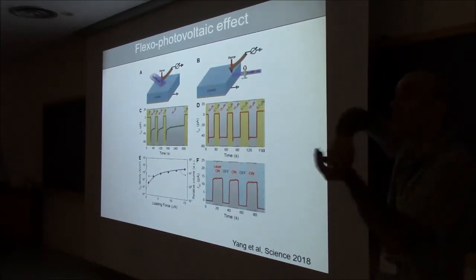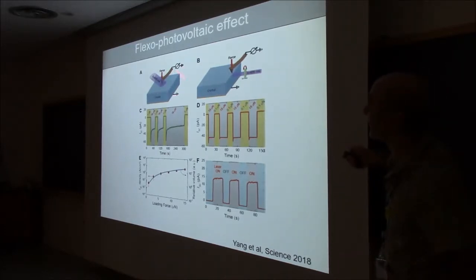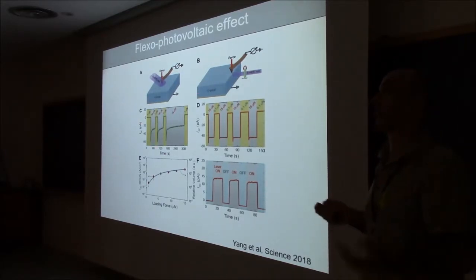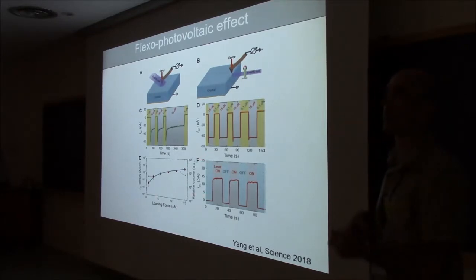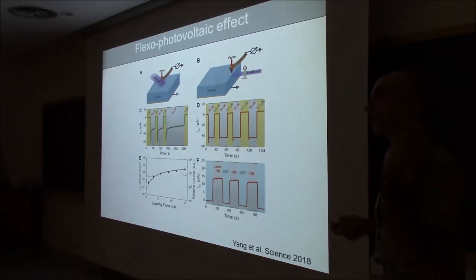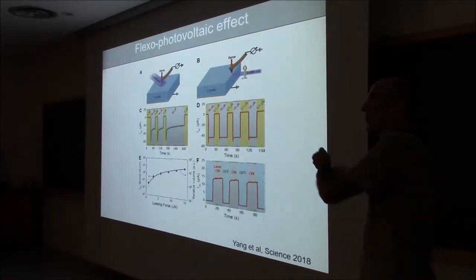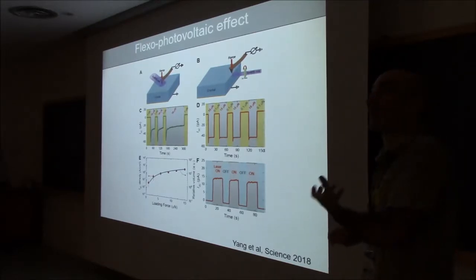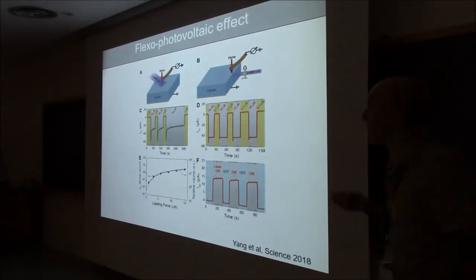He took an AFM tip, he pushed with the tip of the AFM on the crystal. Under the tip of the AFM you break the symmetry, and so when you shine light, a photocurrent appears. And how much photocurrent you get is proportional to how hard you're pushing on the surface. So they attribute this to a flexoelectric effect. Basically, flexoelectricity turns your material effectively into a polar material, whereby the bulk photovoltaic effect can exist. And this was done with insulators.